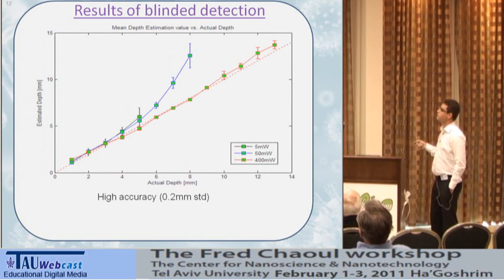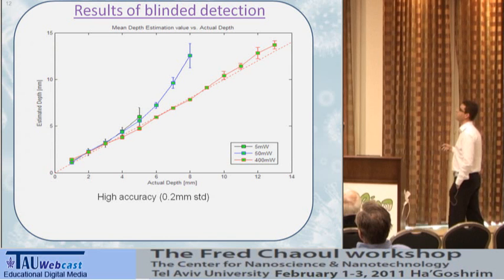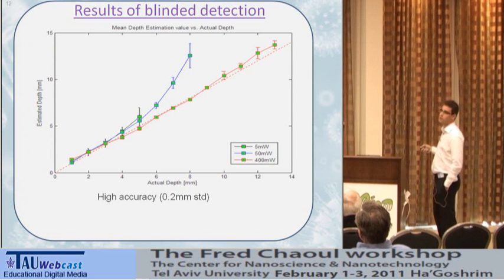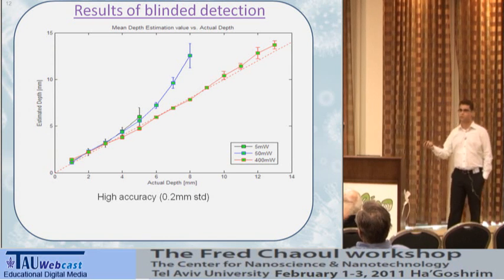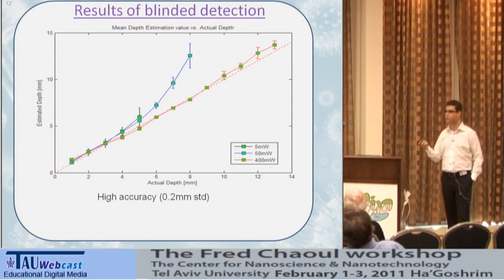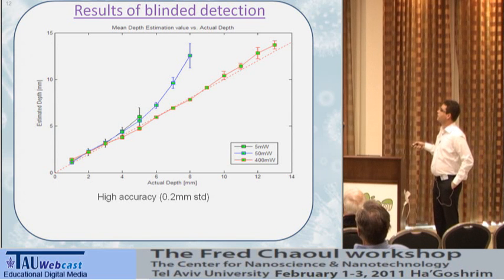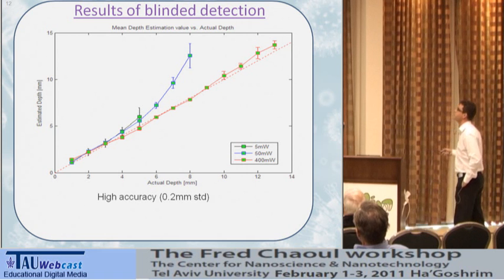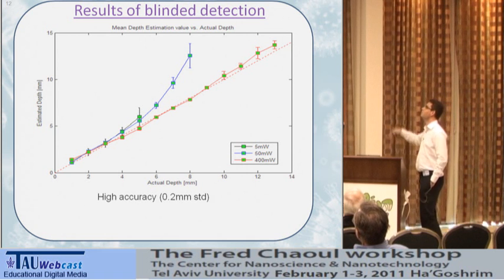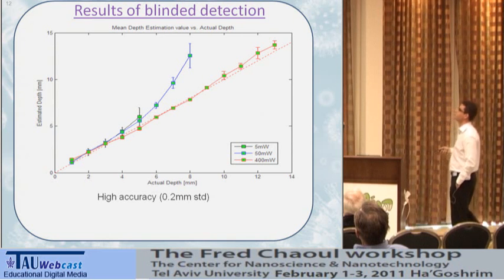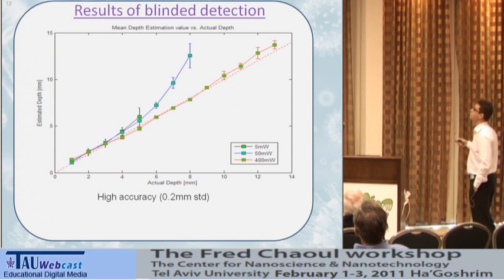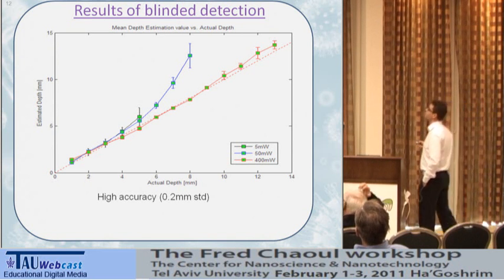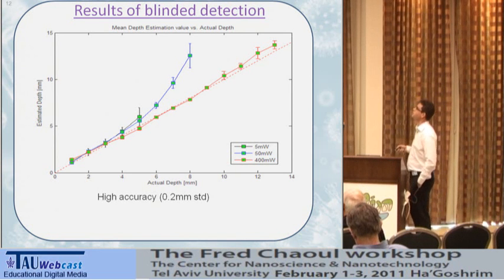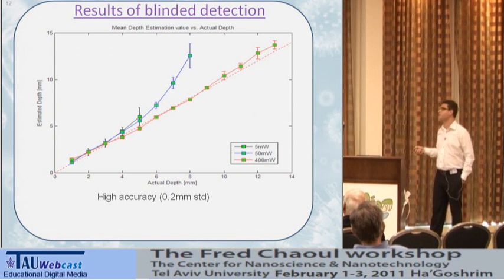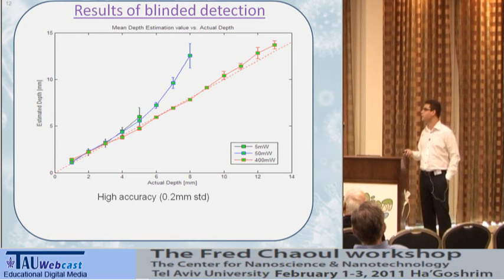Anyway, the next thing we wanted to test was our estimation algorithm. We wanted to see how well we estimate the depth of the tumor. And again, for 400 milliwatts of heating, which is the maximum performance that we can achieve, we see that up to 13 millimeters we can estimate the depth quite well, with a standard deviation of 0.2 millimeter.